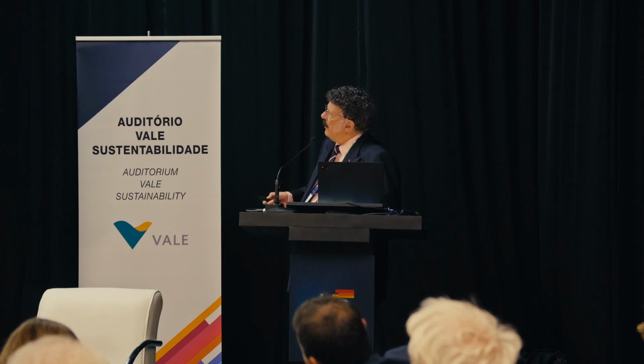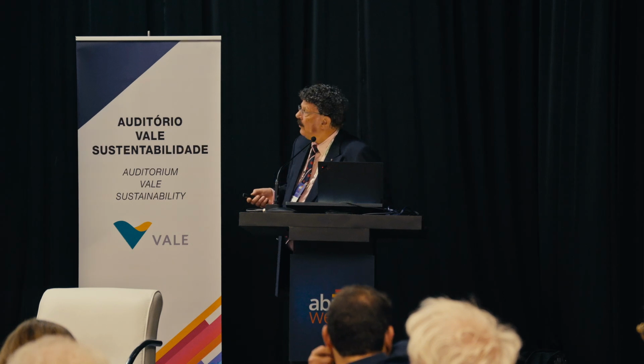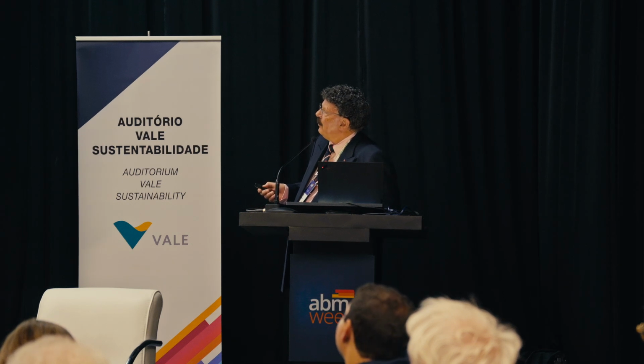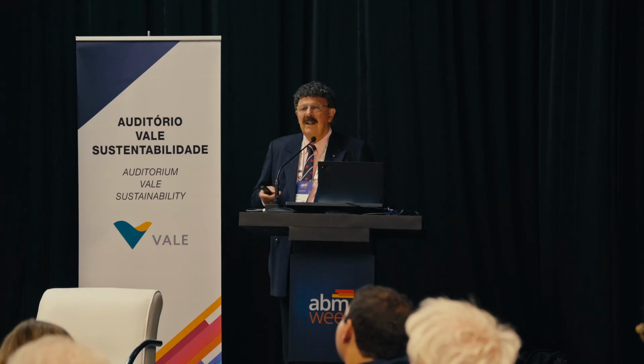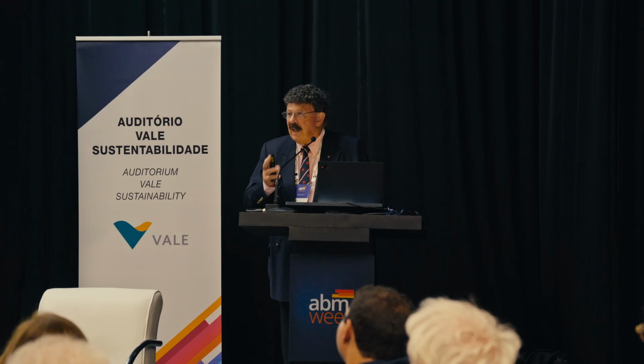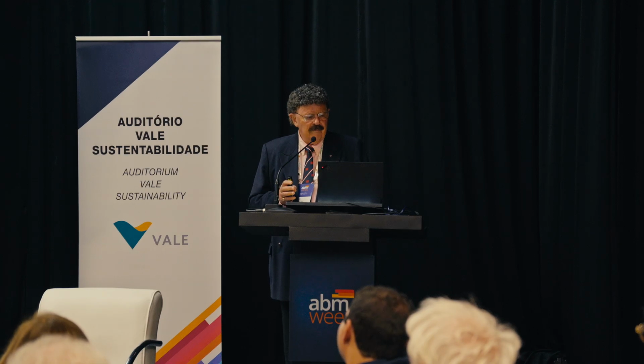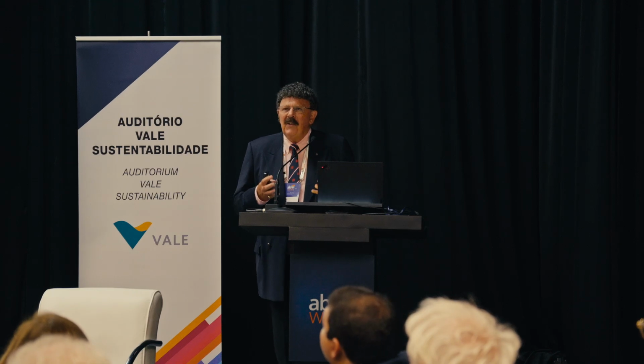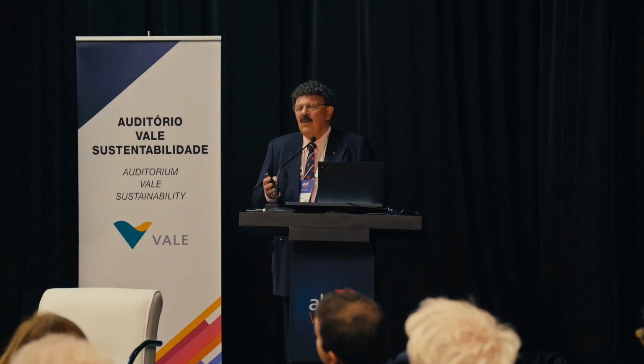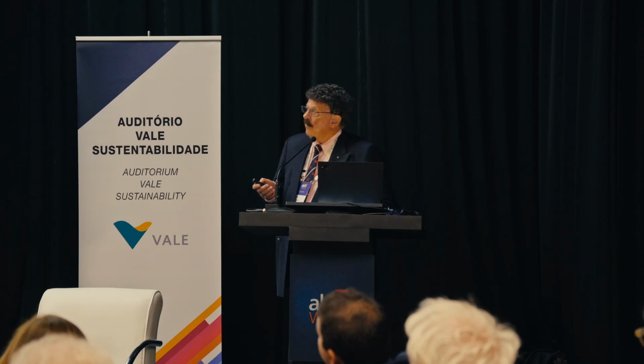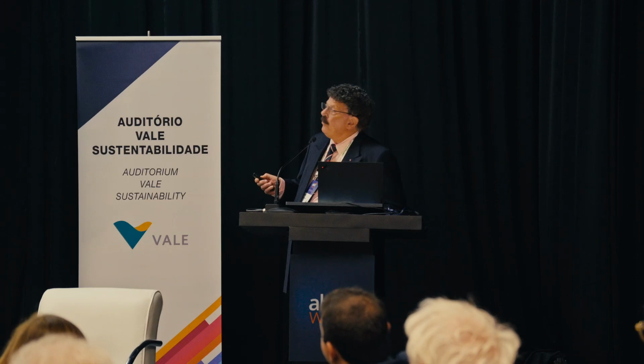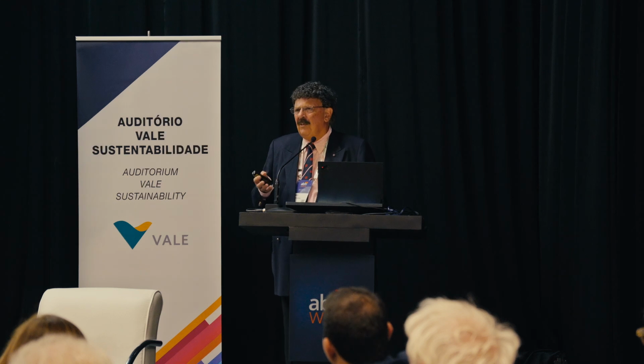There's the banana curve again, and this alloy is way up here, which is not what we expected. It's high strength because it's a BCC material, but not as high as some, of course, but it has high ductility. And this is in tension, not in compression. Why? Well, one of the intriguing things about this alloy is it has a sequence of deformation mechanisms. By the way, it doesn't show strain hardening. The FCC material strain hardened. These alloys have no strain hardening at all, which is intriguing.